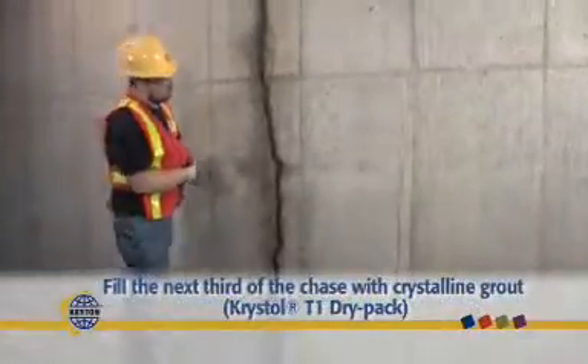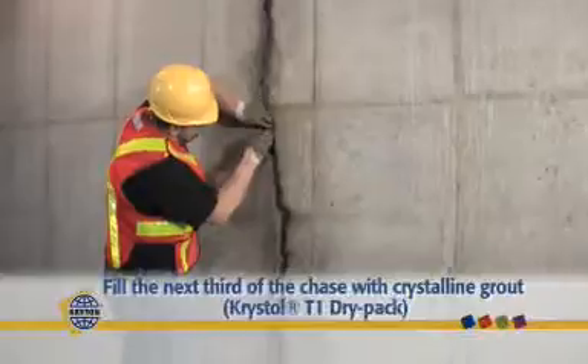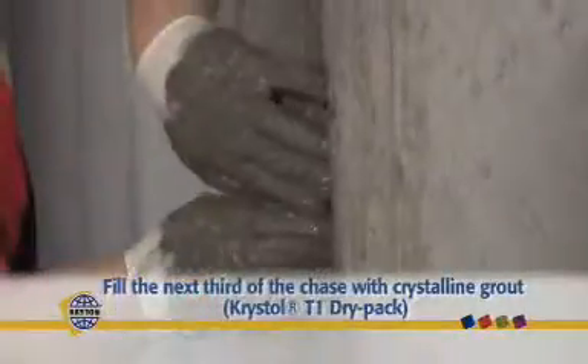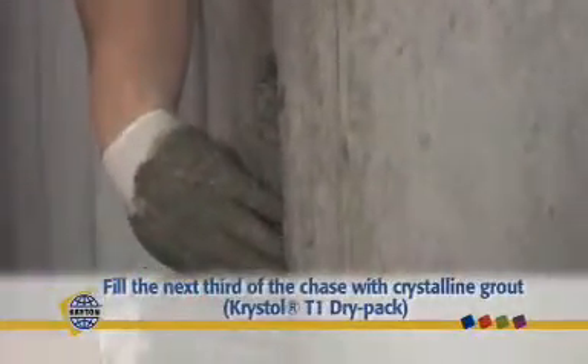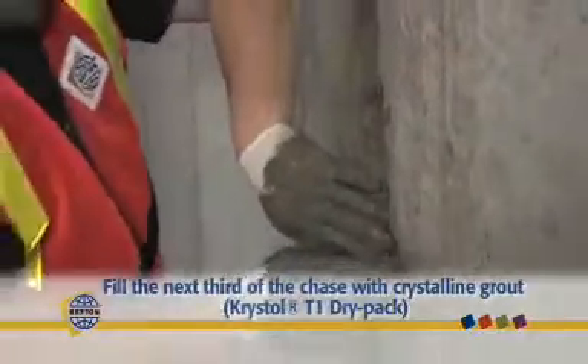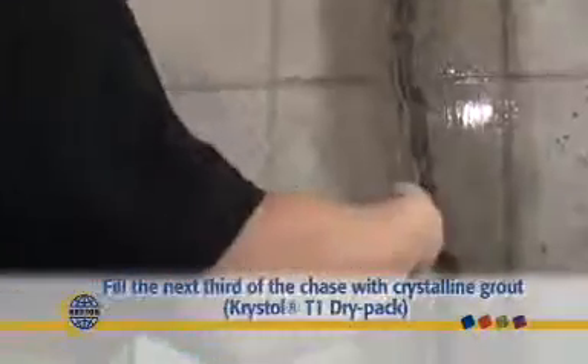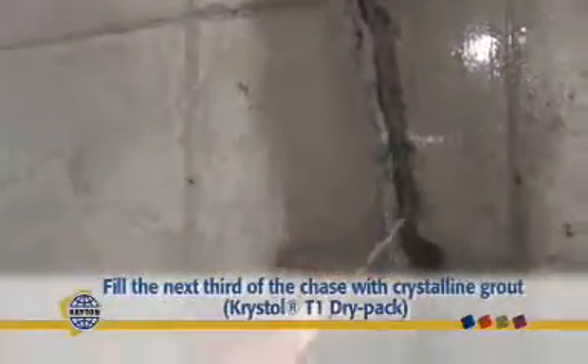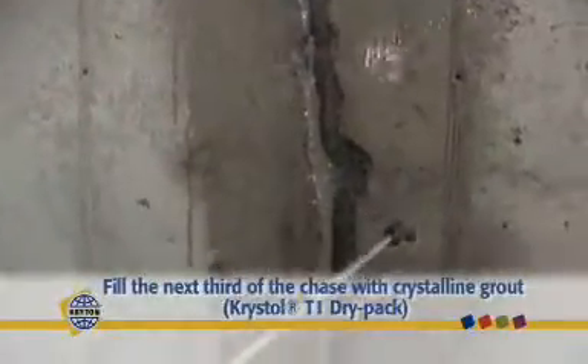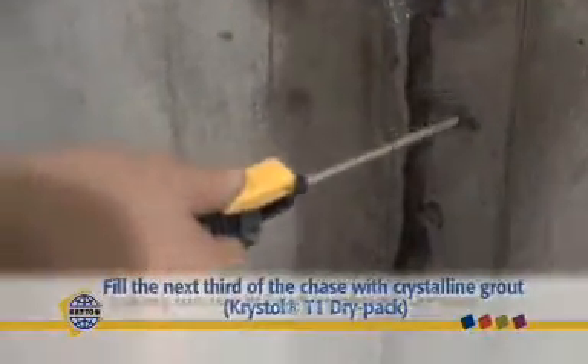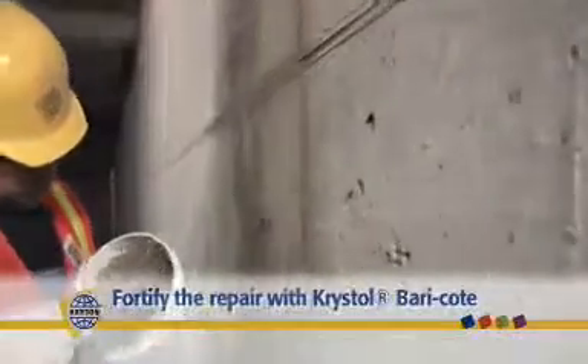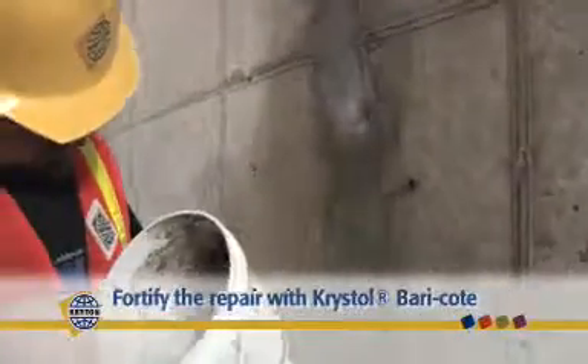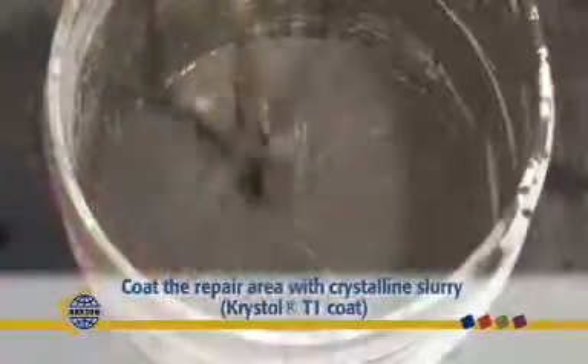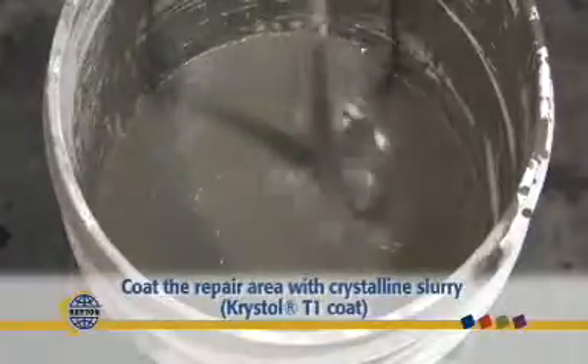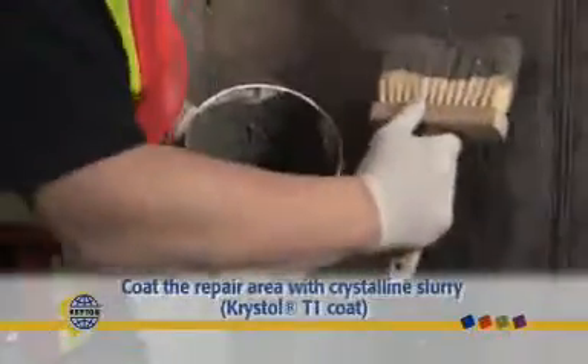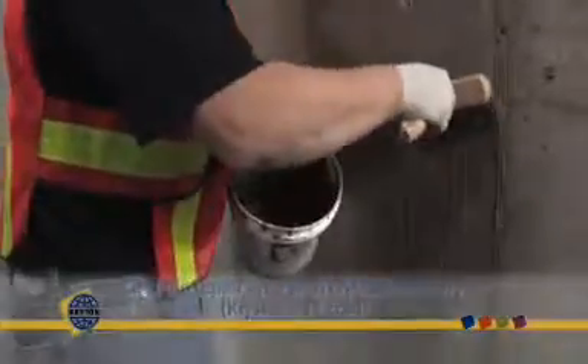Then fill the next third of the chase with Kryton T1 in a dry pack form. It is important to maintain the crack in a surface-saturated dry condition for optimum Kryton growth. The chase should now be 2/3 full. Once Kryton T1 is sufficiently cured, approximately 2 hours, fill the chase flush to the surface with Kryton Baracoat. For complete protection, coat the repair area with the Kryton surface treatment method, a 2-part cementitious slurry application.